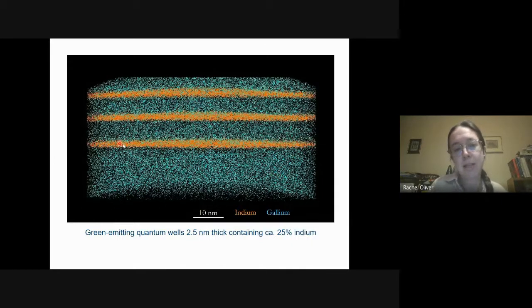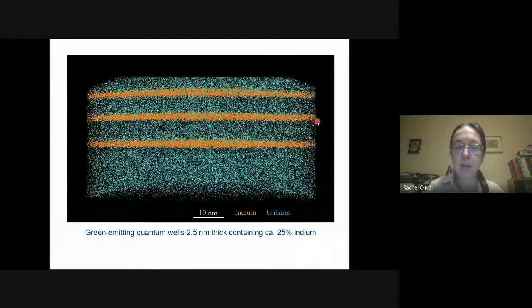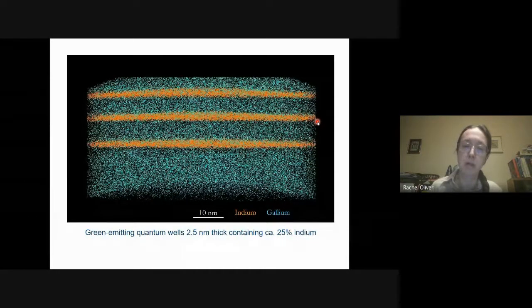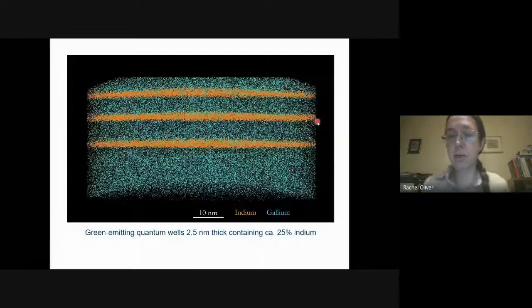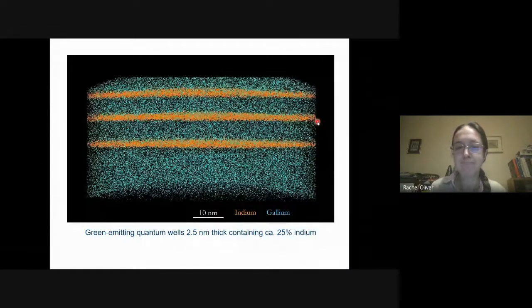But all we can really see is just these stripes of indium. It's not obvious whether there might be compositional variations within the indium gallium nitride. And that's partly because this is a projection through the whole of our 100 nanometer diameter needle-shaped specimen. So it's difficult to see any variations in composition because of how they superpose on one another.